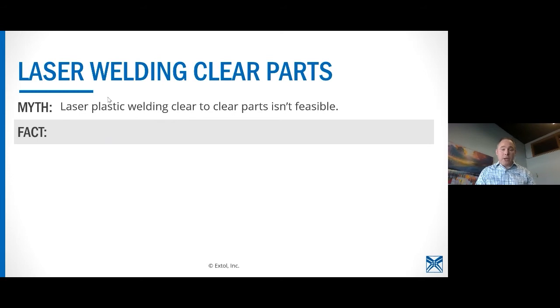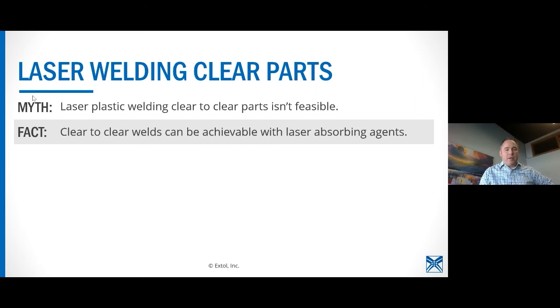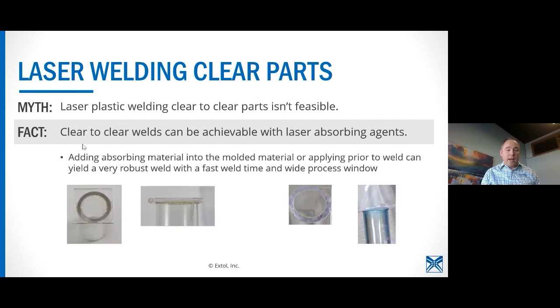So let's talk about clear parts. Well, you talked all about this absorptive layer, right? It's key. We've got to make sure we have that. But the fact is, clear-to-clear welds can be achieved with laser absorbing agents. Adding an absorbing material into the molded material or prior to the welding topically can yield a very robust and quite fast weld time with a wide process window. These are just 2 examples. The one on the left is an excellent supplier that we've used, Clearweld, and the one on the right's a different company.